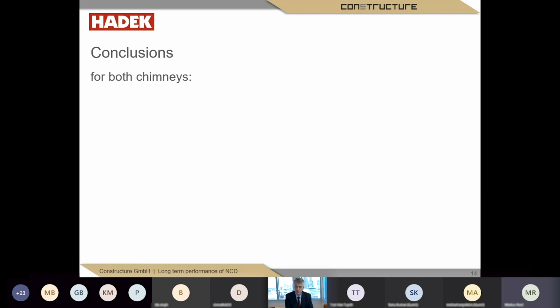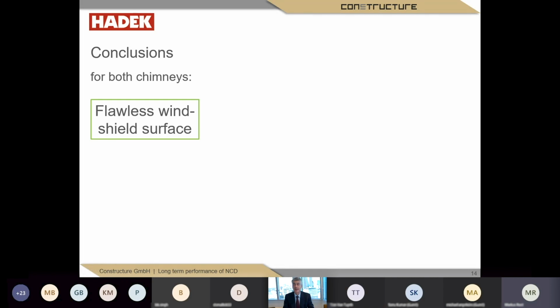The conclusion for both chimneys can be described with three headlines. We detected on both examples flawless windshield surfaces with cracks of very limited width of about 0.1 millimeter, which is fully acceptable and quite typical for this new chimney design and in accordance with all requirements of the individual regulations. This is the result of the flawless lining surface.